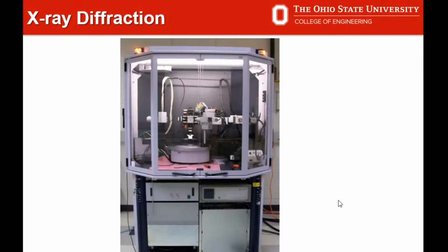X-ray diffraction is another thing. After growing the materials, again, you'd like to check the structural quality. Any structure of a material could be crystalline, polycrystalline, or amorphous. If you get just one single, very high and dominant peak with a narrow line width, that is called single crystalline. If you're getting multiple peaks, that is called polycrystalline. And if you get no observable peak, then that is called amorphous.